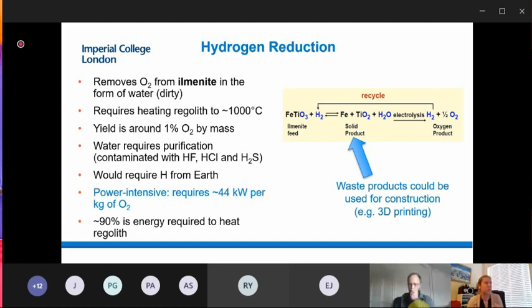The water requires purification, and this is an area that has been under-researched. But it's incredibly power-intensive. Even the lowest temperature of the technologies that I mentioned on the previous slide requires around 44 kilowatts per kilo of oxygen. Most of that is required as heat to heat the regolith. So we can see some of the challenges that are there, and it produces maybe 1% of oxygen by mass, so our yields are low.